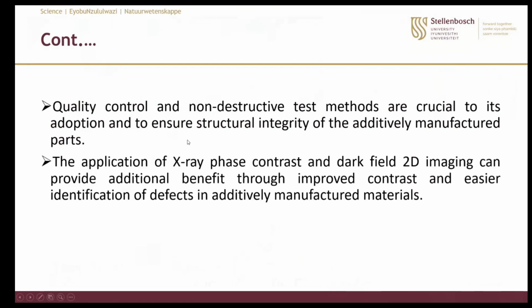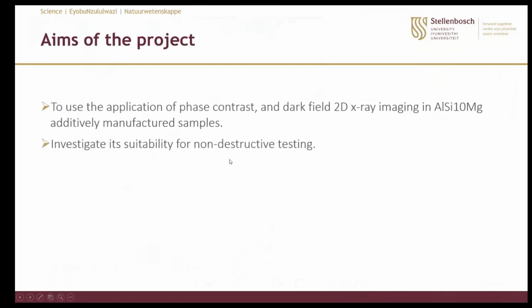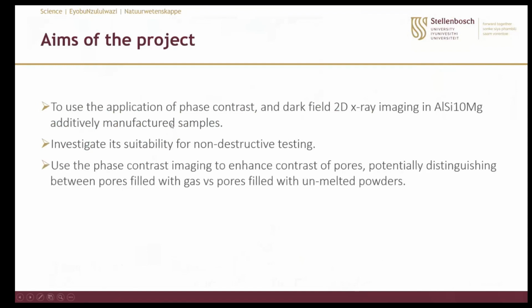Therefore, the application of X-ray phase contrast and dark field 2D imaging can provide additional benefit through improved contrast and easier identification of defects in additively manufactured parts. The main aim of my study is to apply phase contrast and dark field 2D imaging on aluminum alloy additively manufactured samples. The purpose is to see whether I will be able to detect intentionally created porosity with various distributions, like open pores and pores with some trapped powder in them.